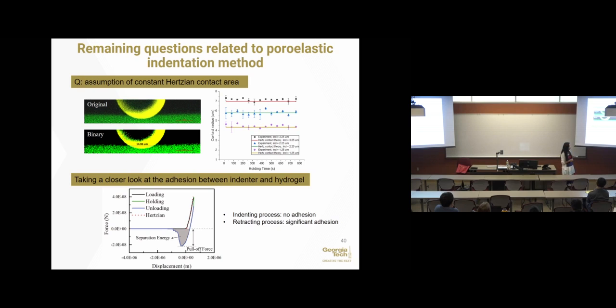But when you retract it, you see significant adhesion. So it does develop adhesion between the indenter and the gel over time during holding, but it doesn't influence the force profile that you measure. This is the so-called adhesion hysteresis. This is very interesting. I won't have time to tell you in this talk today, but we have a theory to look at this time-dependent adhesion hysteresis as well.